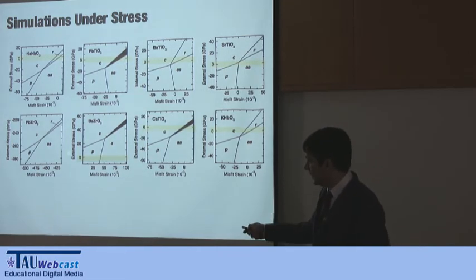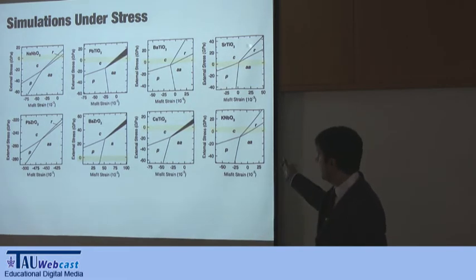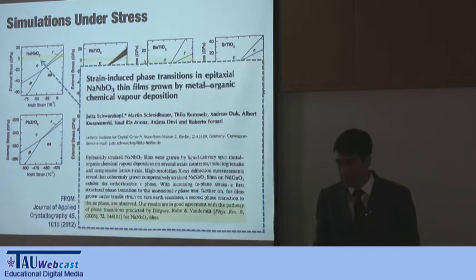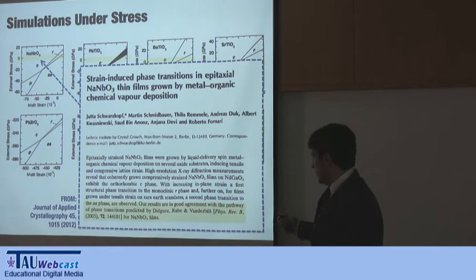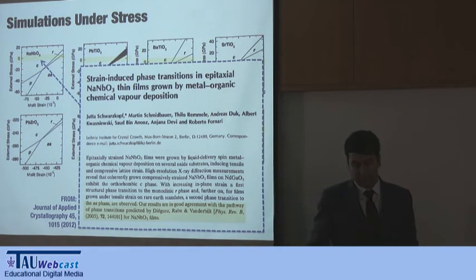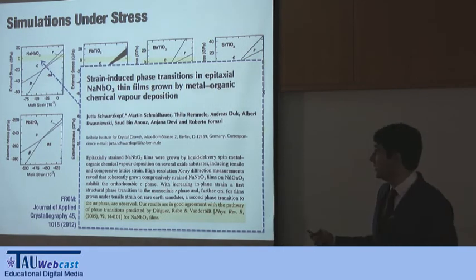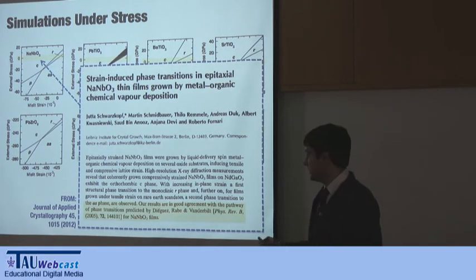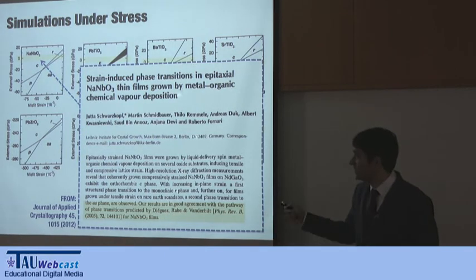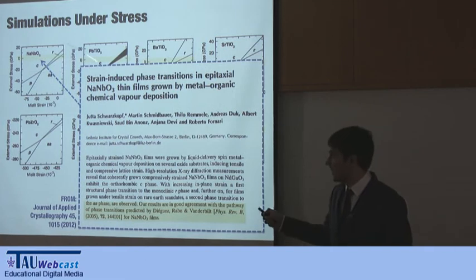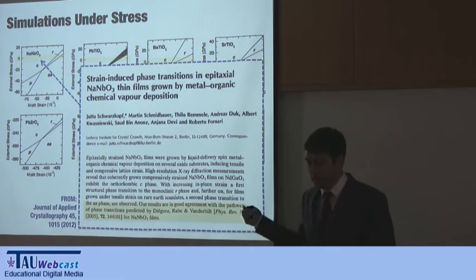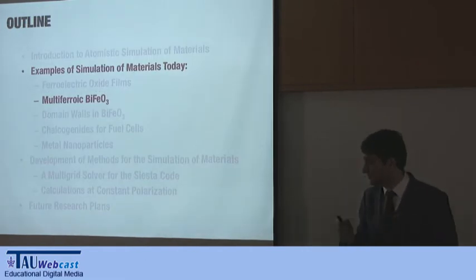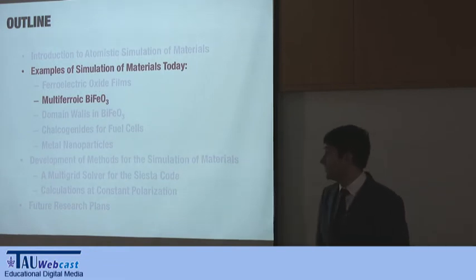So this material looks very different from this material because it has 2 different phases, but it's just another part of the phase diagram. It's also good when the experimental results agree with whatever you predict. So this is an example in which this group measured these films and agreed with our results. So that's for ferroelectric films.